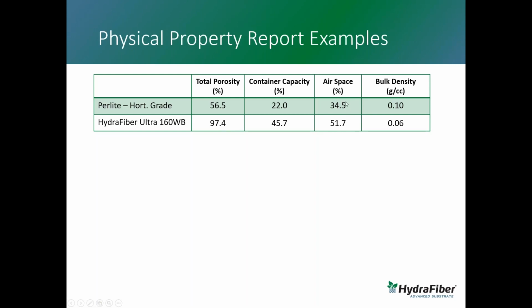However, what's really amazing to me is when we look at the airspace. With the horticultural grade Perlite, we have a lot of airspace. That's what Perlite has historically been used for. Whereas Hydra Fiber has even more airspace. So not only does it have more water holding capacity, but it also has a lot more airspace than the Perlite does. And why is this? Well, the reason again goes back to total porosity. In the case of Perlite, we have a relatively low total porosity compared to Hydra Fiber 160. And so that allows us in many instances to not really sacrifice water holding capacity in the mix when we use Hydra Fiber in place of Perlite, and we still can have a better oxygenated root zone than Perlite.